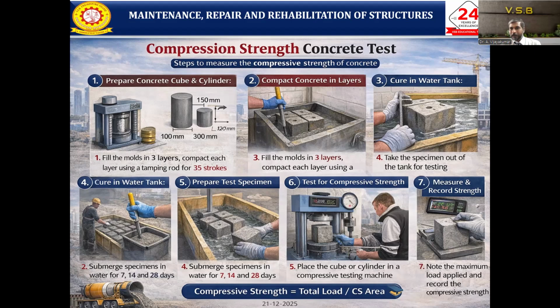Suppose I made M20 concrete. My compressive strength should not be less than 20 Newton per mm square. Likewise, if I'm making a trial mix of M30 or M40 concrete, we follow the same standard procedure and conduct the test. Our value should not be less than 30 or 40 Newton per mm square. Then only can we achieve the proper composition. This is one of the prime methods of assessing the strength of concrete for cubes and cylinders.